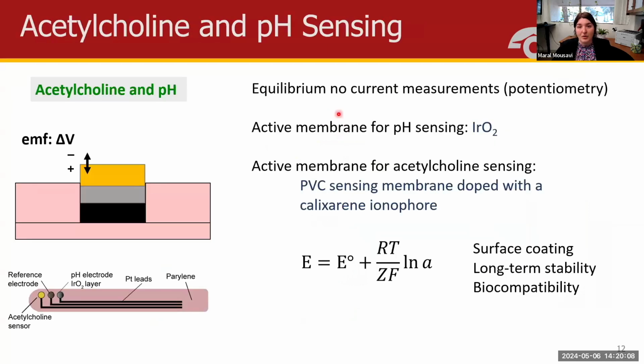So the second module I want to talk about is our acetylcholine and pH sensing. In this system, we're not actually doing any oxidation or reduction. This is still electrochemical measurement, but it relies on equilibrium open circuit potential measurements. We're not really pushing current. We're using the distribution of pH or acetylcholine across a sensing membrane to generate a surface charge.